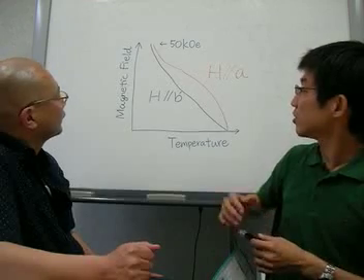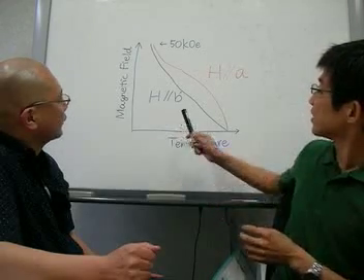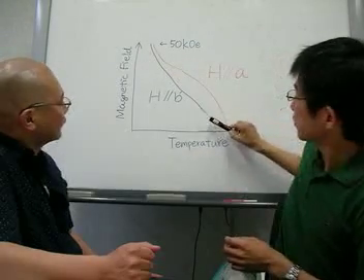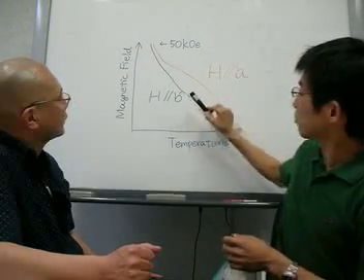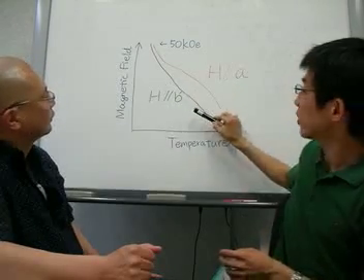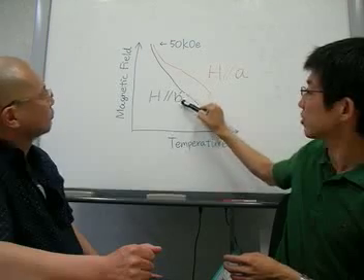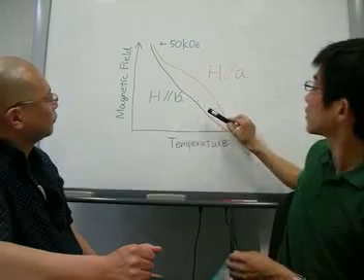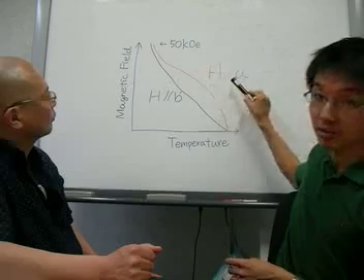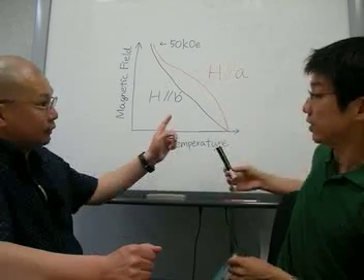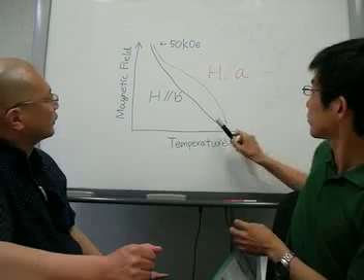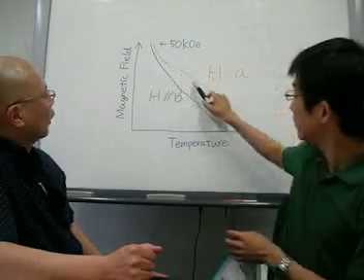And it's more unusual because this blue curve is a boundary between superconductivity state and the normal state when magnetic field is parallel to the b direction. But when we apply magnetic field to A direction, another crystal direction, the boundary is like this red curve.